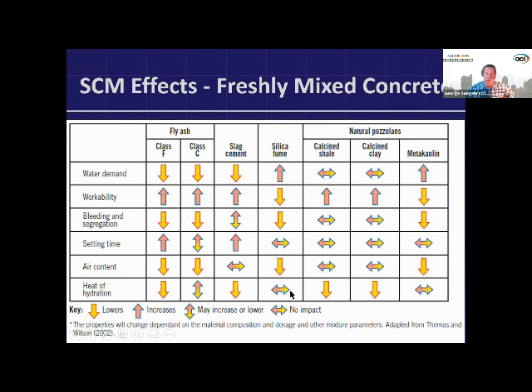Silica fume is more for the reduction in permeability, because silica fume particles are about 100 times finer than a cement grain particle, and hence we get the lower permeabilities with the use of silica fume. Of course, it has a high water demand because at that small speck size, it adds a lot of surface area to the mix. As you see up here in workability, it brings workability down. So that's something you would have to counter with an admixture to maintain the low water-cement ratios. Okay, I'm getting off the curing topic.